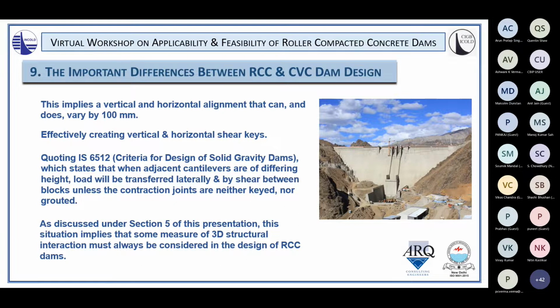And as discussed under section 5 of this presentation, this situation implies that some measure of three-dimensional structural interaction must always be considered in the design of RCC dams. We are creating these shear keys, and in a situation of low stress relaxation creep, we have joints that don't open very much. So we have shear keys that will transfer load between adjacent blocks. And this may not be relevant on a long level gravity dam of similar section, but certainly is on a site where the abutments are steep and the crest length is not excessive.